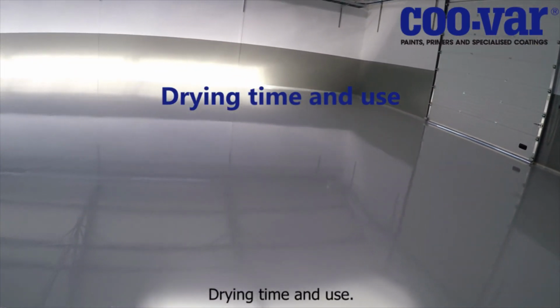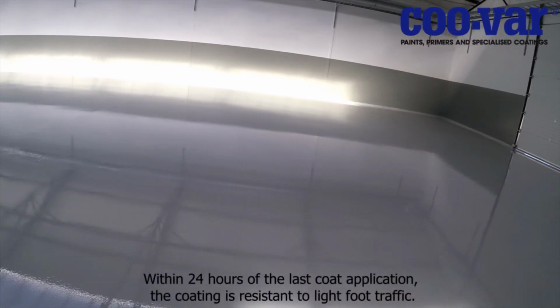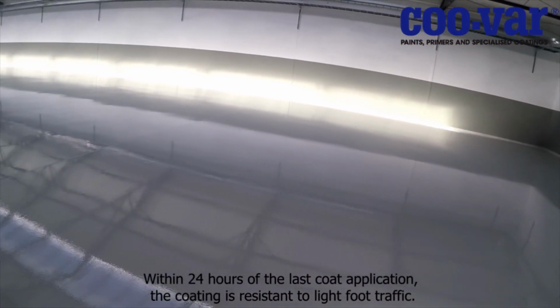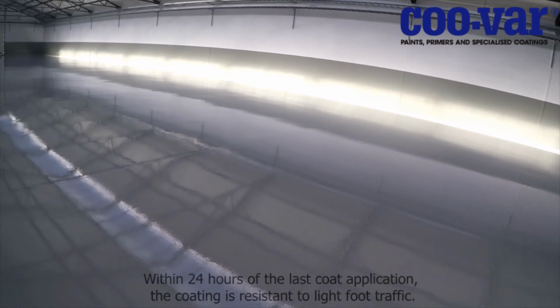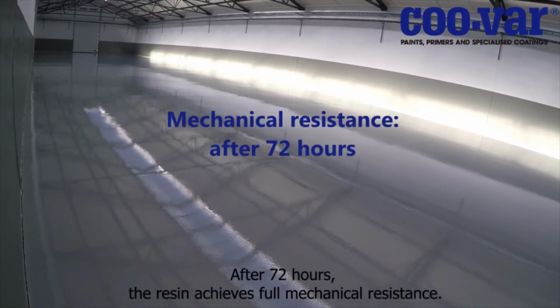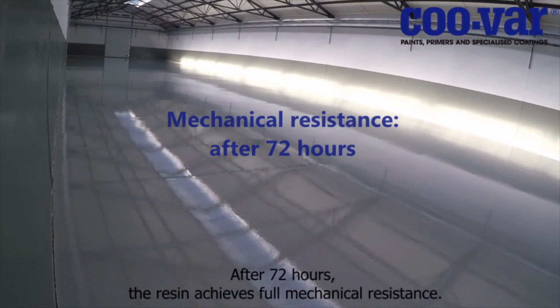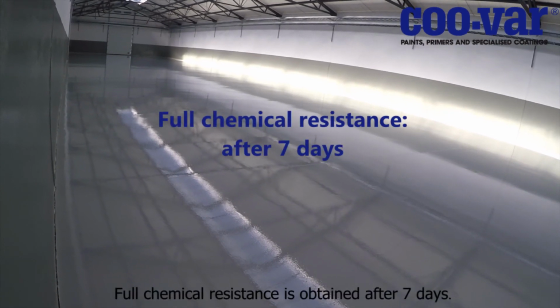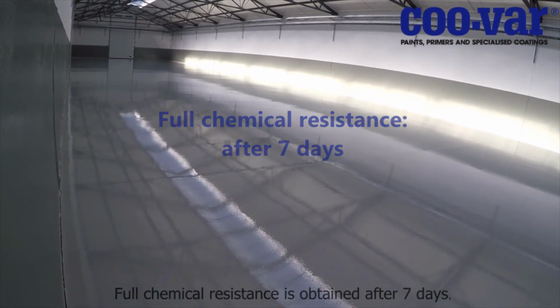Drying time and use. Within 24 hours of the last coat application, the coating is resistant to light foot traffic. After 72 hours, the resin achieves full mechanical resistance. Full chemical resistance is obtained after 7 days.